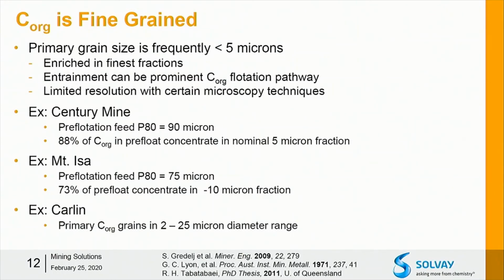Okay, and this has 2 real big impacts on flotation. The first is that carbon may actually float very, very slowly, not because of its surface chemistry, but because of its particle size. Fine particles frequently float slow. The second thing is that entrainment becomes a really prominent mechanism for carbon to report to a concentrate. So even if you have a perfectly effective depressant, you still may have a lot of trouble actually depressing carbon because of frothing issues, because of entrainment, and not because your depressant doesn't work. So this is, again, a reason why pre-flotation, given the entrainment factor, can really be a good process to consider.